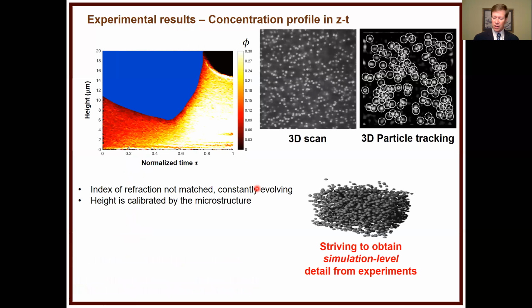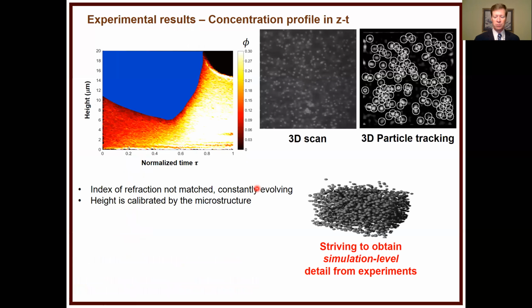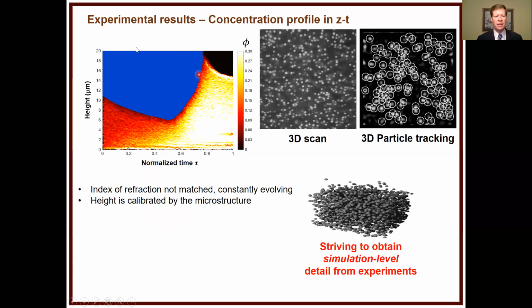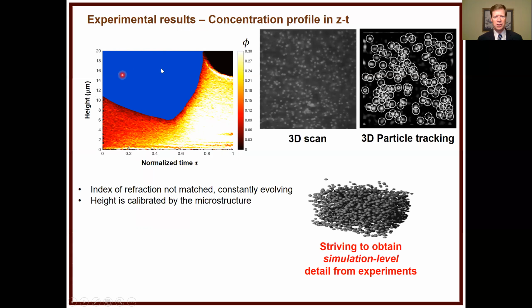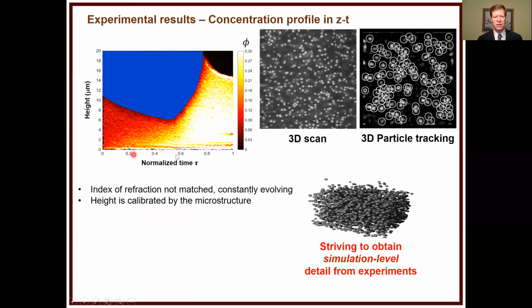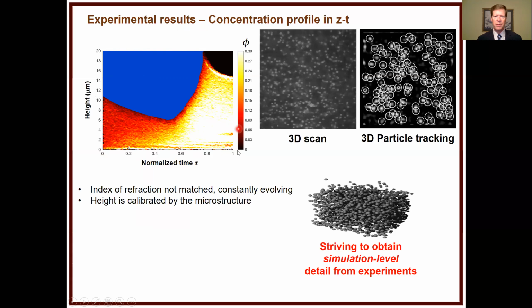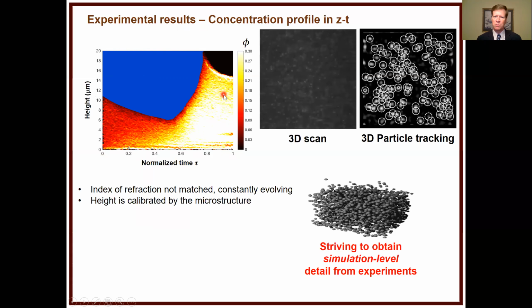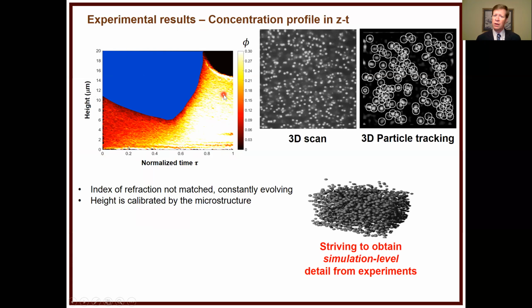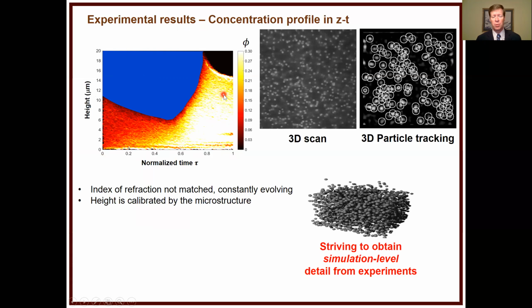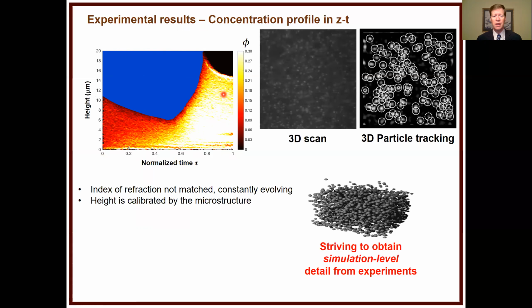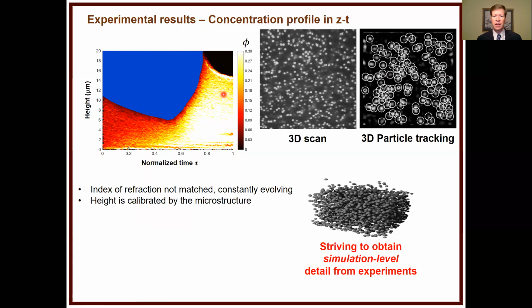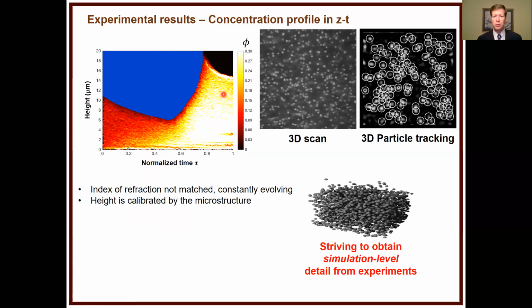Just to start, I'm going to give you a time evolution profile of the drying process. You can think of this as the height from the substrate, and then the time during drying, where time equals 1, essentially the microstructure is arrested. There is a little bit of residual water still diffusing through the polymer and colloid matrix, but essentially we don't expect any more microstructural rearrangements at this point.